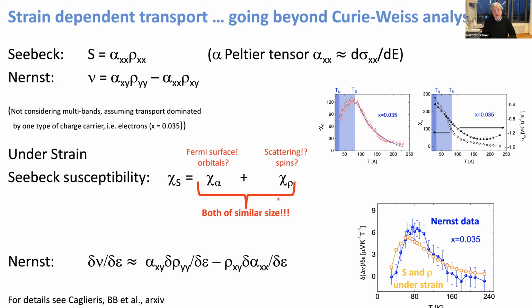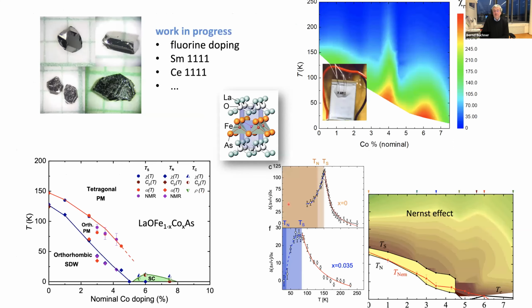What we did then is to take these susceptibilities, which we derived experimentally, to model the Nernst effect. We can do that along these lines, and details are described in this paper. And again, without any assumption, without any fitting parameter, you can reproduce the Nernst data from thermopower and resistivity and from their strain derivatives. That by itself is already a funny story, a very unusual thing, but it tells us that this approach, having these two kinds of susceptibilities, two kinds of strain dependence, makes a lot of sense. Okay, that's what I wanted to tell you today.